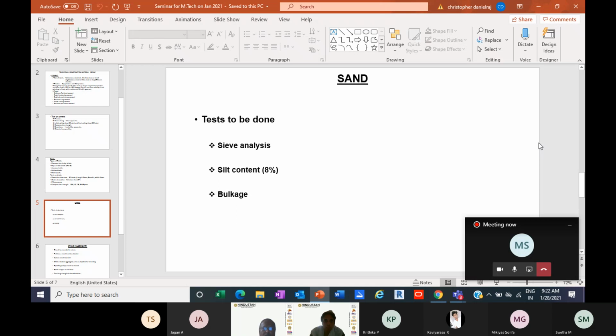So this water cement ratio we have to follow very strictly, then only the strength of the concrete can be achieved. If the sand has a lot of moisture in it, that moisture will add to the water content of the concrete, and that will disturb the water cement ratio. That is why this bulkage test we have to do daily. Whenever concreting is done, on the morning of the day of concreting we have to do the bulkage test and find out how much extra water has to be added more than what is available in the sand. That will form the basis of addition of water in your concrete.